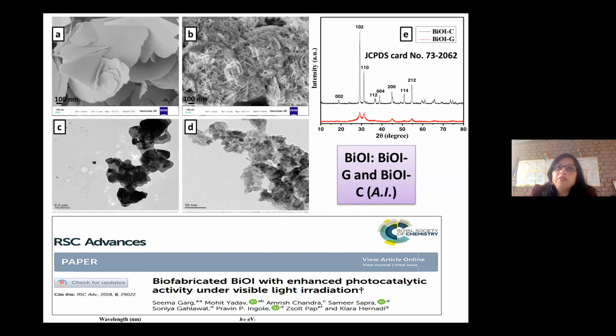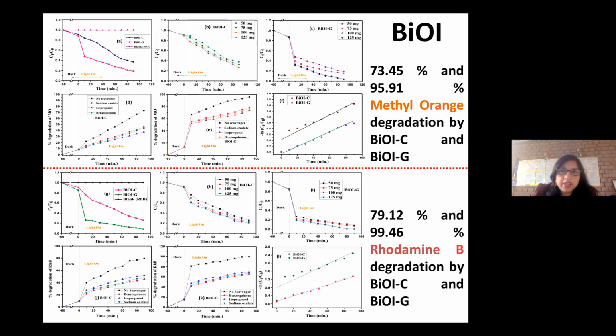But if we prepared it with the green one, we found it is giving the best result among all bismuth oxyhalides. Because the green method is separating the electron holes, it is giving better results. You can see the peaks are broader here, so it shows the nano, and these are the bigger. A and C are the hydrolysis method, bigger plates, and here the one prepared by the green method shows the nano, and the paper was published in RSC Advances.